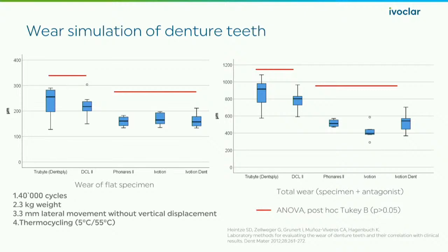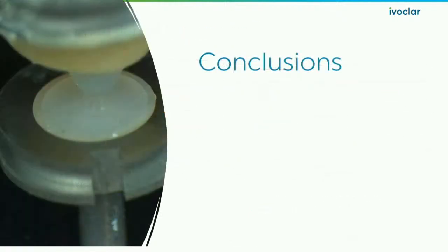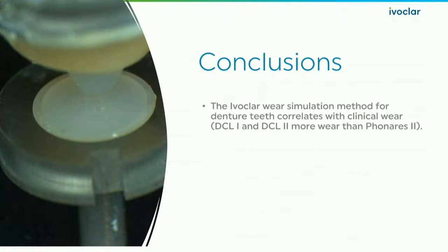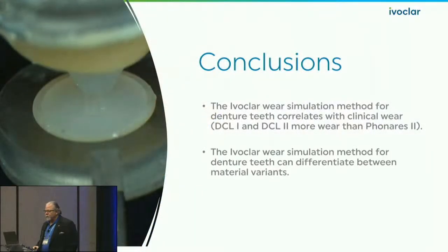When you're in front of a wear machine in the lab, and it just sits there and does 10,000 cycles of wear going in a little circle, you know, that's just that one movement. But when you get into the dynamic of the mouth and the position of the teeth and where things are happening, they get a little bit more wear. But it was interesting. It stayed consistent with what we were seeing in the lab studies. And so around 600, when you include the standard deviation, was about where we wanted to be with the tooth material. So what we found was that the wear simulation of the teeth correlates with the clinical wear, like I talked about. The DCL1 and DCL2, we have now 3 generations of DCL material, you know, they wore more than the Phonares II did, which was obvious.